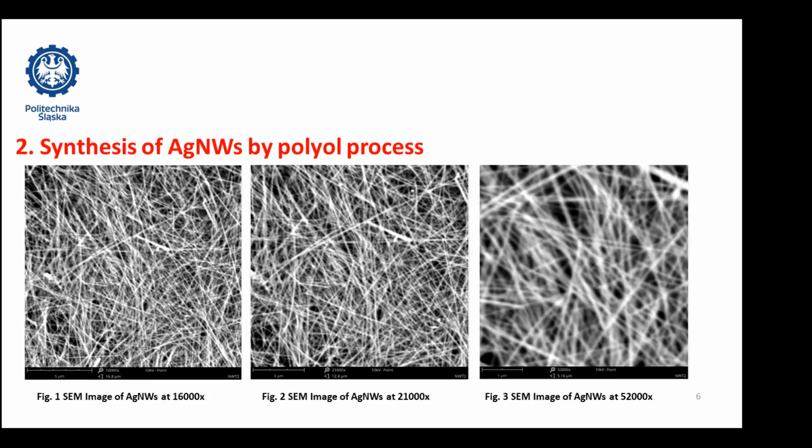And coming to the last one, copper(II) chloride. Copper(II) chloride is a mediating agent. When it dissolves into the solution, it turns into copper ions and chloride ions. The chloride ions act as an oxygen scavenger, while copper(II) chloride has two main functions. First, it electrostatically stabilizes the silver seeds, and second, it prevents the accumulation of an undesirably high concentration of silver ions by making poorly soluble silver chloride salt.